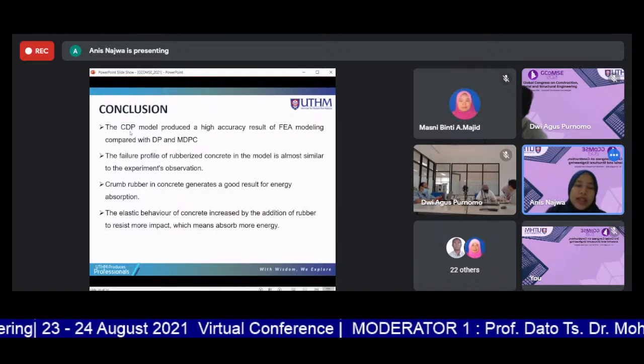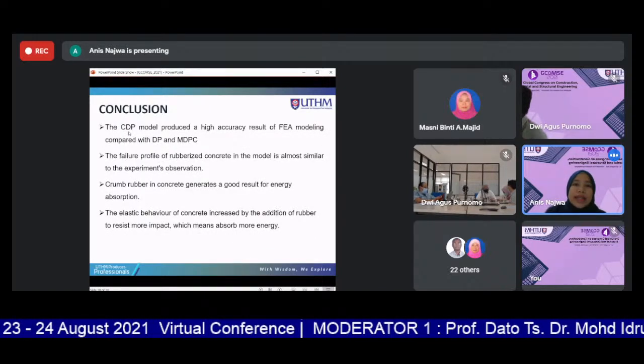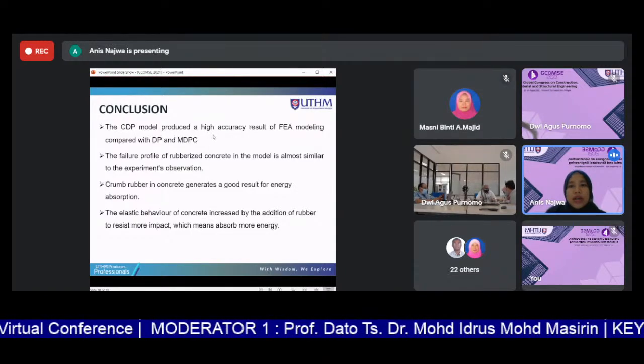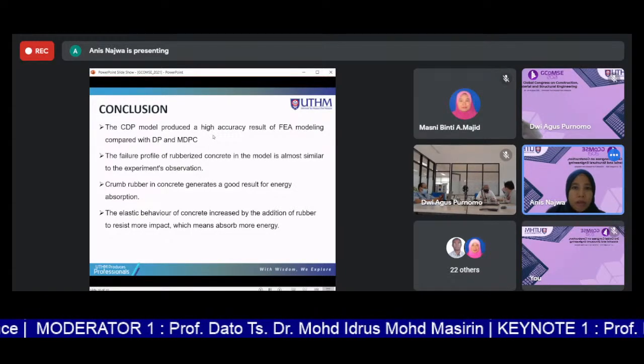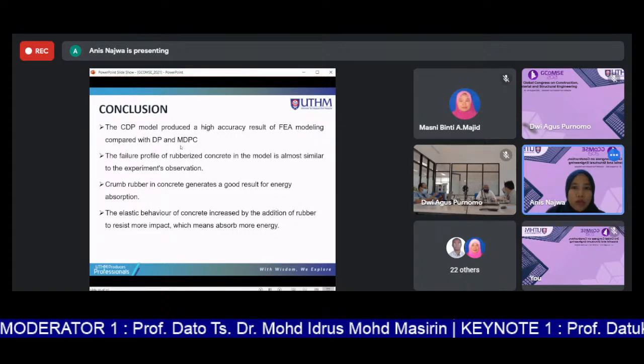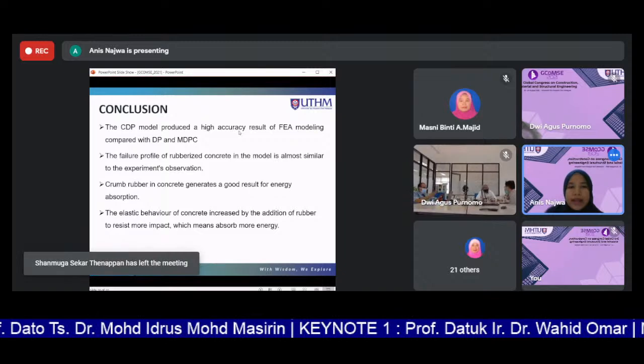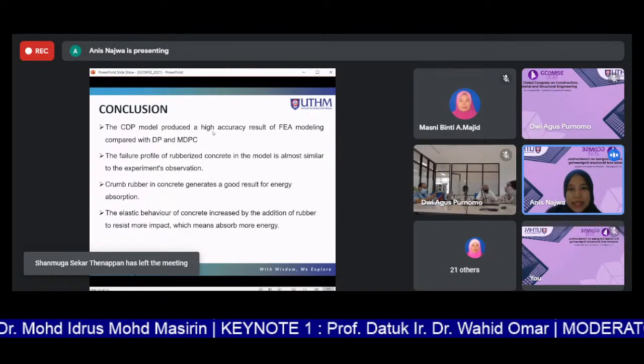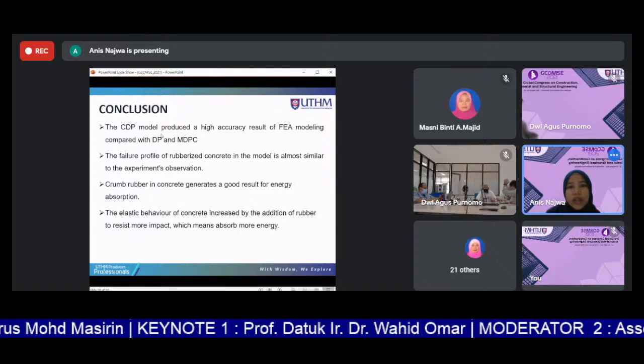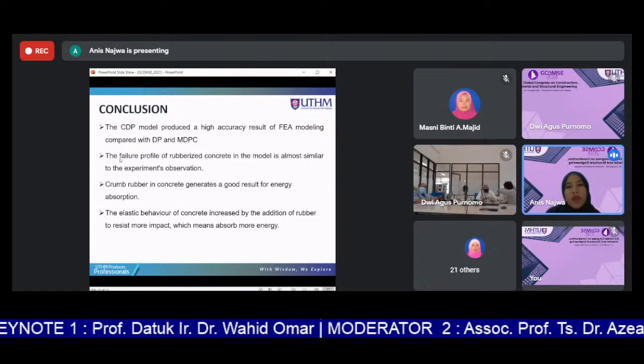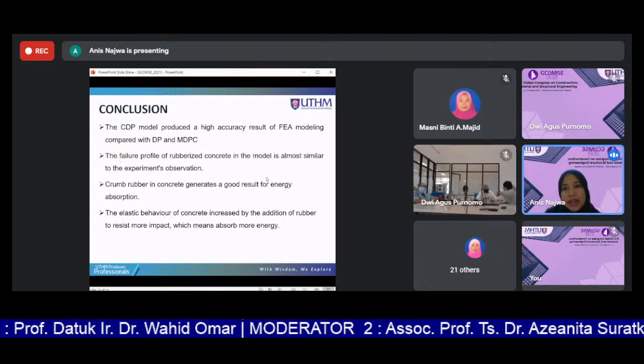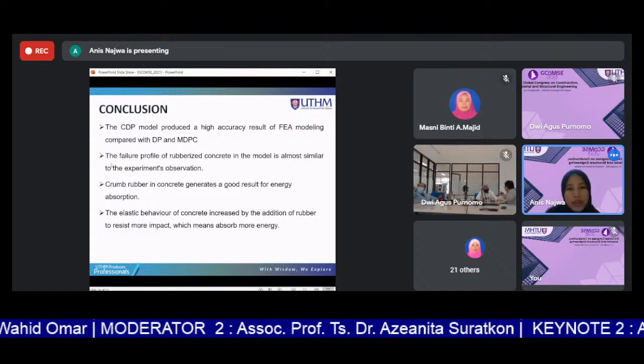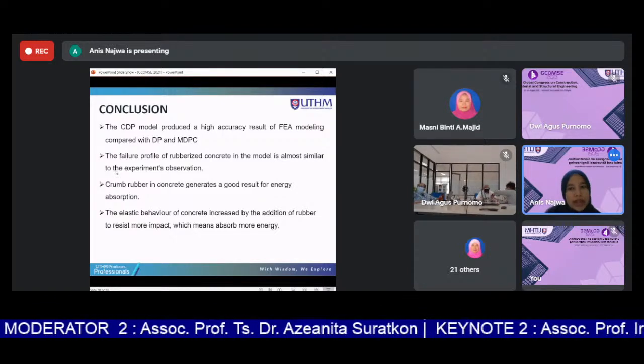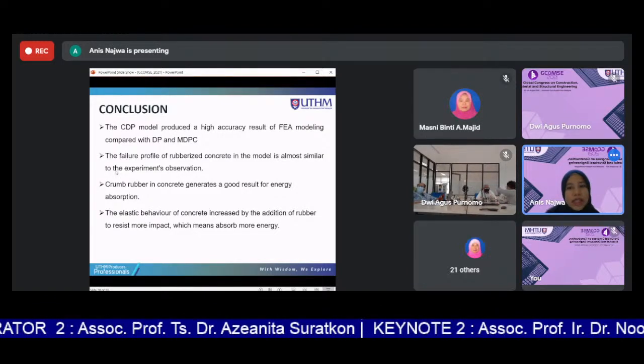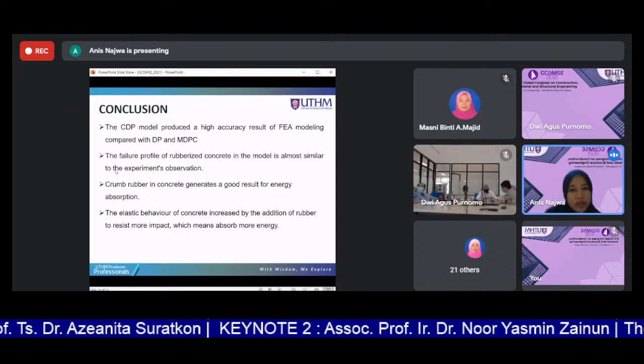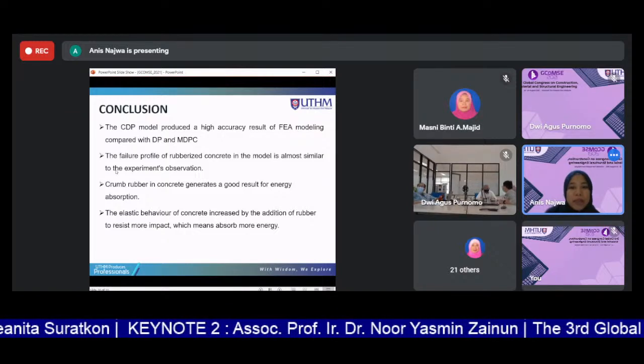So for the conclusions, it shows that the CDP, the concrete damage plasticity model, produced a highly accurate result in FEA modeling compared with DP and also MDPC. It clearly showed in the previous slide that concrete damage plasticity gives a good result, which is closer to the experimental result. And the failure profile of the rubberized concrete in the model is almost similar to the experimental observations. So it's quite good. And then the crumb rubber in concrete actually generates a good result for energy absorption. Therefore, the elastic behavior of concrete is increased by the addition of rubber to resist more impact,